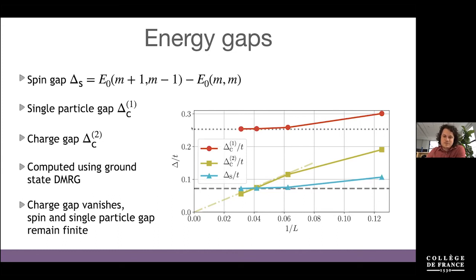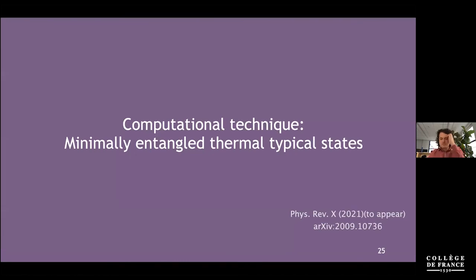So what is our conclusion? On this cylinder, we think the gap of the single particle excitations is still sizable. However, it is smallest close to this nodal region. And we find there's no charge gap, since scaling the charge gap with the length of the cylinder extrapolates exactly to 0. So let me switch gears a little bit. I hope this got you interested, that we can get some really nice new results on this Hubbard model.